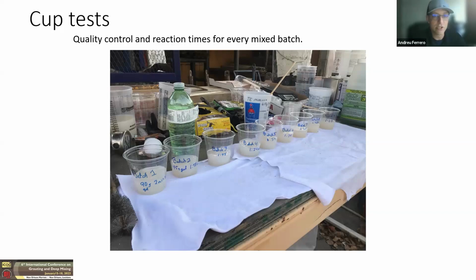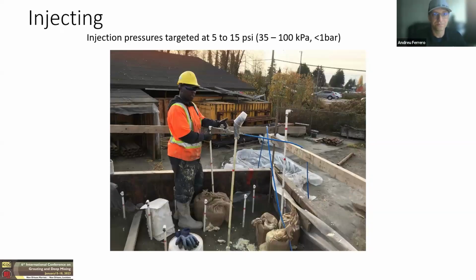So when these materials are injected into the soils, that reaction time will be delayed because these reactions are exothermic. The catalysts generate heat within the materials, which creates the reaction. So the soil absorbs some of that heat, so it takes a little bit longer for that material to react. With, on average, a 1 minute and 45-second cup test reaction time, you're going to get about a 5.5 to 6 minute reaction time in the soil, which extends the amount of permeation you can do and makes that permeation sphere bigger the longer the set time is.